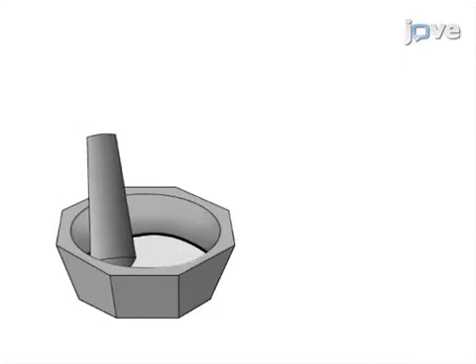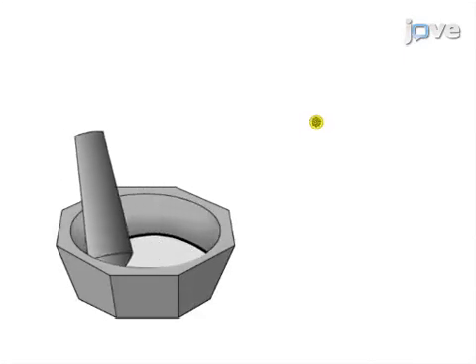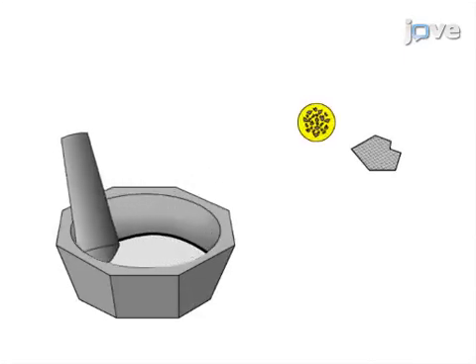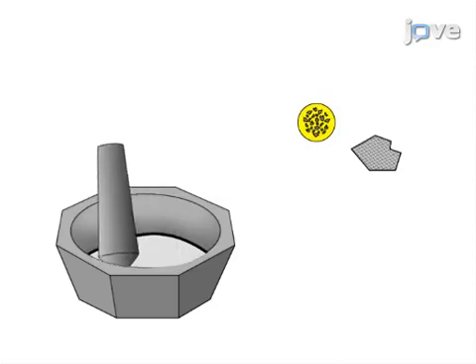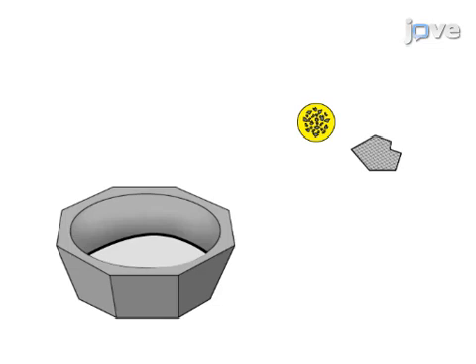Highly siderophile elements are introduced as gold-coated beads or sintered mixtures of platinum, iridium, and iron. By either physically separating HSEs from the silicate melt or introducing a strong reducing agent, the formation of metal inclusions that complicate chemical analysis can be avoided.